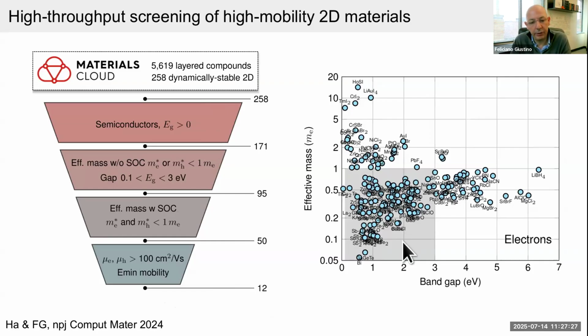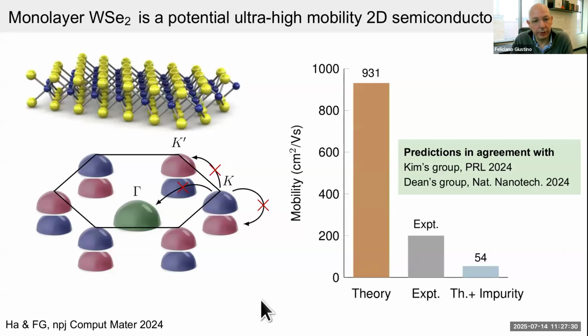So with this, we did a lot of work performing these high-throughput calculations, and I'm just going to give you the final result in the interest of time. Even though we considered many compounds, some of them not yet synthesized, it turns out that our calculations brought us back to a compound which is tungsten diselenide, which is pretty common in the world of two-dimensional materials. Our framework predicted that this compound should exhibit a carrier mobility in the range of 1,000 centimeters squared per volt second, which would be extraordinary for transistor applications.